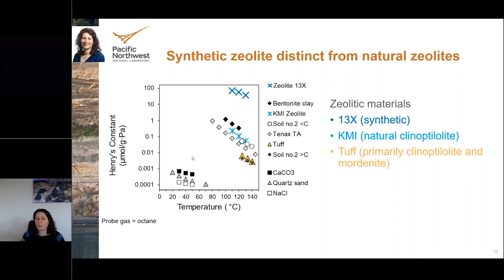They're more similar to the more absorptive geologic materials we had analyzed previously, so like the soils and the clays. But really notably, zeolite 13X, the synthetic zeolite, is distinct from the natural zeolites as well as the other materials. And this really stands out. So in terms of magnitude, the partition coefficient for the synthetic zeolite is nearly two orders of magnitude greater than other zeolites. And I think this really just speaks to those properties that I mentioned, the absorptive properties and molecular sieve, that people use zeolites commercially for.